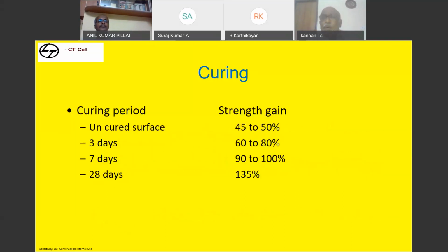Generally, an uncured surface of concrete, if no curing is done at all, gives only 45 to 50% strength. If I cure the concrete for 3 days, it gives 60 to 80% strength. If I cure it for 7 days, it gives 90 to 100% strength. If I cure it for 28 days, it gives 135%. Again, I am telling you, curing means keeping the area moist, so that the internal water will not evaporate. That's all.